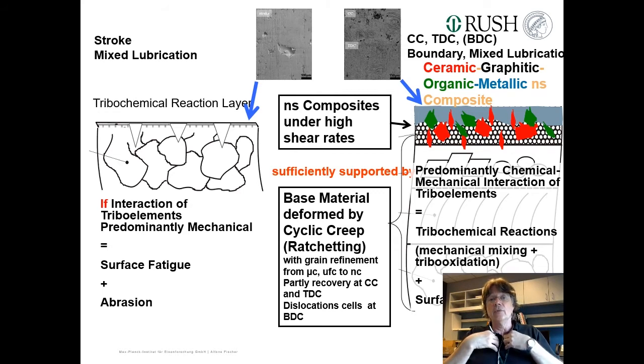So I found out with my car, which is a diesel engine, I have 50 nanometers that gave me the 220,000 kilometers that I rode that car in the meantime, mostly on the German Autobahn. So if this very thin shear band, which is very soft if you shear it, and which is able to accommodate these extreme shear rates without just falling off the surface, is supported well enough by the underlying strain gradient. You know, every thin coating has to be supported well, otherwise it cannot show that it's a wear-resistant coating. So this combination, which more or less you get for free, so you get nanocrystalline matter that lasts for a long time for free, if you choose the right metal in combination with the right process for a certain application, you know, you get very, very small wear rates.